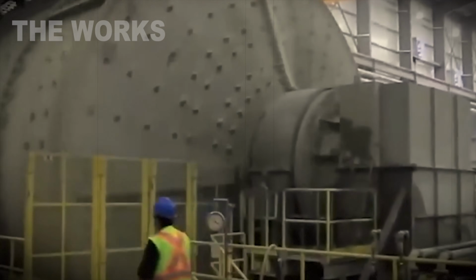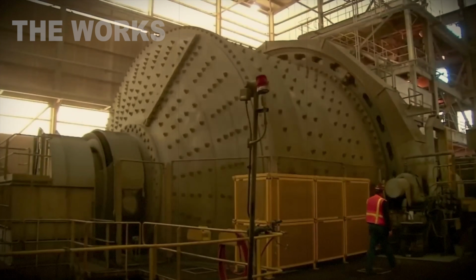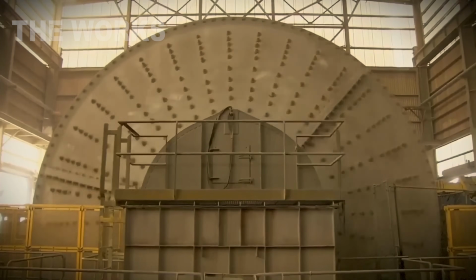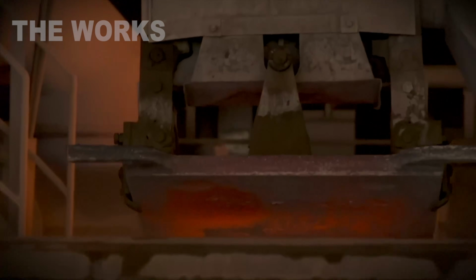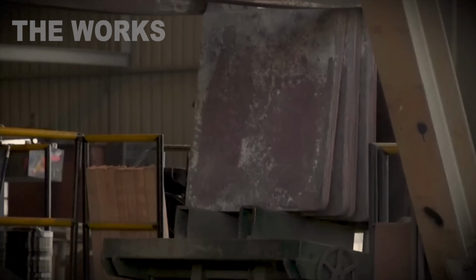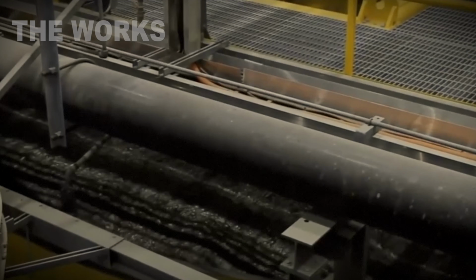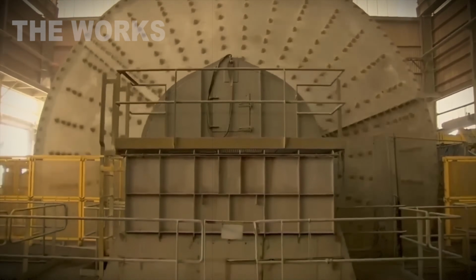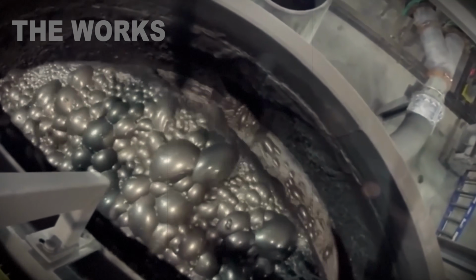This finely ground slurry gets pumped into flotation machines, rectangular tanks holding up to 26,000 gallons each. Special reagents get added, xanthates and frothing agents. Compressed air bubbles up through the slurry from below, creating millions of tiny bubbles. The reagents make the surface of copper minerals hydrophobic. They repel water. Air bubbles stick to the copper particles and drag them to the surface as foam.